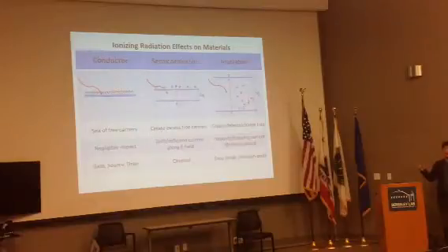So they are often localized, and they act as localized trapped charge. So when this space radiation interacts with the insulating material around the transistor, the positive charges are trapped, and the density of the positive traps increases over time. So the defects created in the insulator act as an aging mechanism.